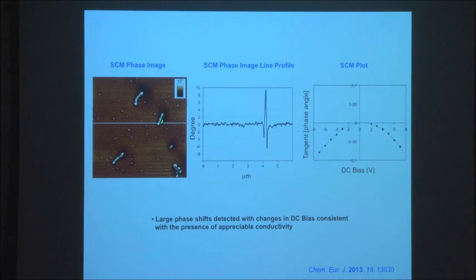So here's an illustration of some of the results. This is one of these emeraldine state coated nanowires looked at by scanning conductance microscopy. A key plot here is the phase angle. It shows the change as you apply the DC bias. And this is typical for a conductive material. So this shows that these structures are conductive. Unfortunately, this non-contact method doesn't give you an absolute value for the conductivity, but it tells you it's conductive, whereas the original micelles are insulating, which you can show by this method. So these structures really are conductive, so you can make well-defined nanowire type structures using this approach.